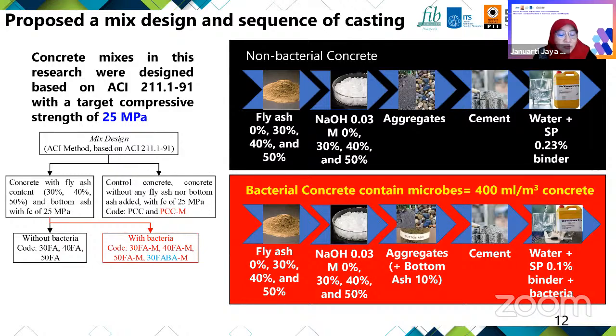And bottom ash was used to replace only 10% of binder weight, but it's actually quite a high amount. We followed a certain sequence of mixing the materials during casting. It is very important because it will affect the workability of the concrete.